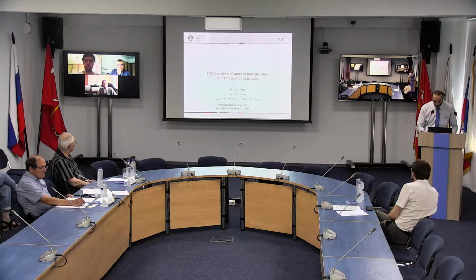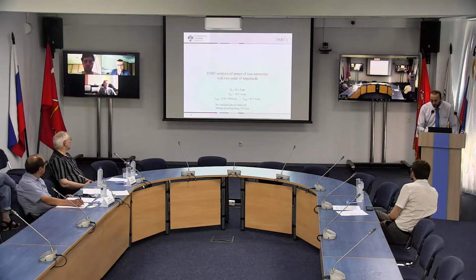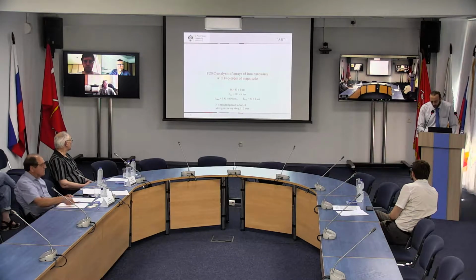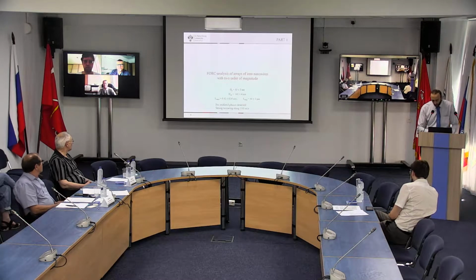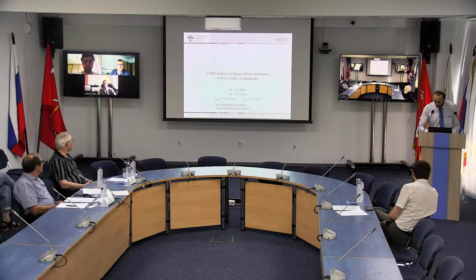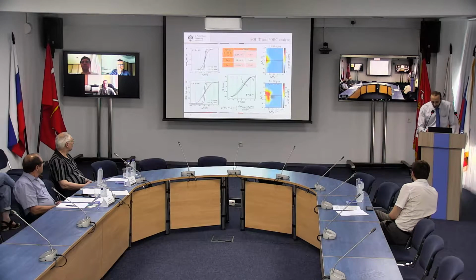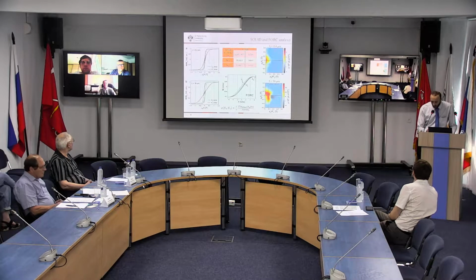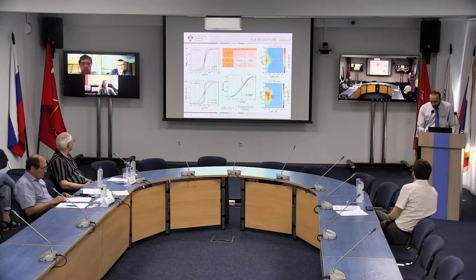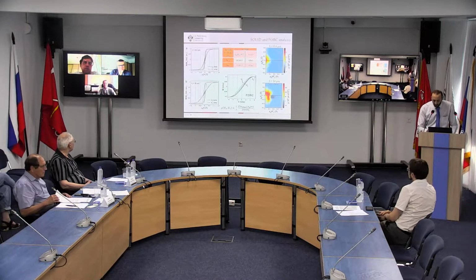In the first part of the dissertation, in order to understand some tendencies for iron nanowires, we have studied samples with lengths of nanowires varying over 2 orders of magnitude by means of SQUID magnetometry and FORC analysis. Here we can see that the magnetization reversal curve showed that the easy axis is directed along the nanowire axis. Also, coercivity as well as squareness increase with length, which according to different models can mean an increase or decrease of interactions. And here comes the role of FORC as an effective method used to investigate these interactions.